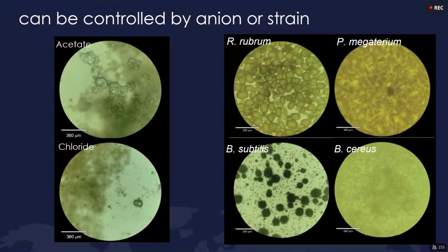The other really cool thing we found is you can control the crystallinity of your particles by changing the microbe you use or the counterion. So if we use calcium acetate versus calcium chloride, we change the size of the particles. These dark spots are just the particles. You can see much larger ones here. And if we just change these strains, these are all soil-derived strains, so we haven't engineered them at all, you can change the crystallinity. So these are calcite and these are vaterite. And so if you want specific kinds of tensile strengths from your construction materials, you can achieve that by just swapping out the microbe you use.